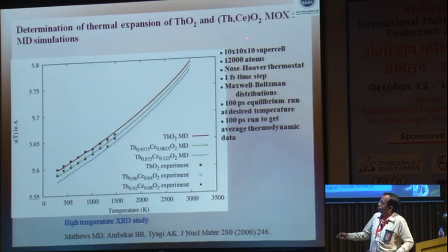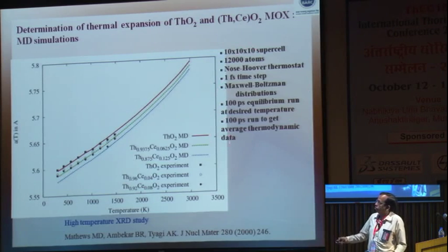Now, for the mixed oxide we have also determined the lattice parameter and the change of lattice parameter, which reflects the thermal expansion as a function of temperature. These are the molecular dynamics simulation values for thorium oxide and the mixed oxide, and these are the experimental values, and you can see that the agreement is quite good. And these are the parameters used for the simulation calculation, and these are self-explanatory.